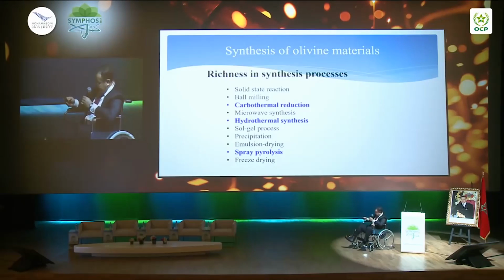Now, you can make this material in different ways: solid-state reaction, ball milling, carbothermal reduction, hydrothermal, which is very dominant now, and spray pyrolysis. I'm going to show you that this could be an interesting opportunity to make very dense iron phosphate to take care of the energy problem if you increase the density.